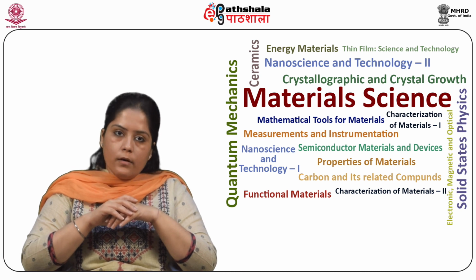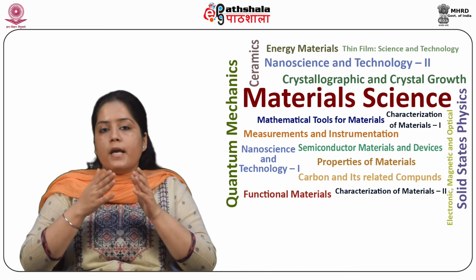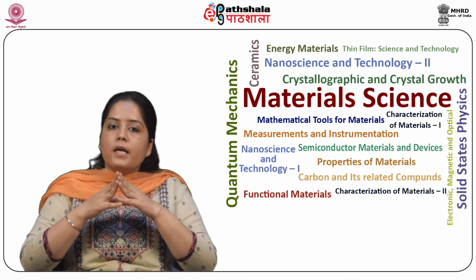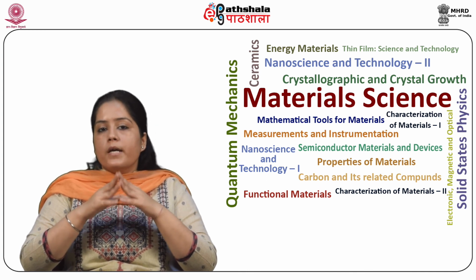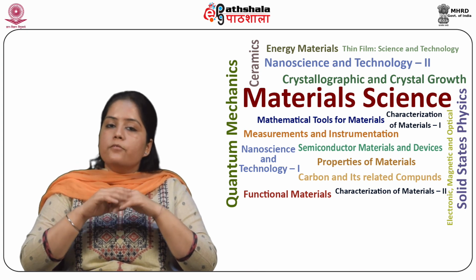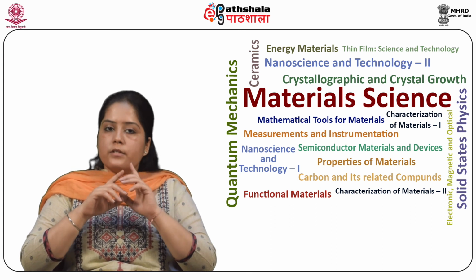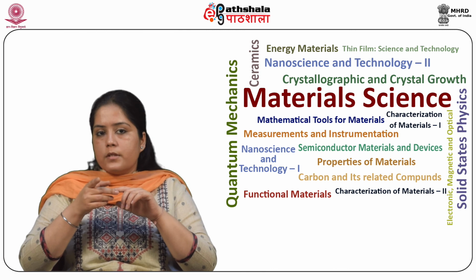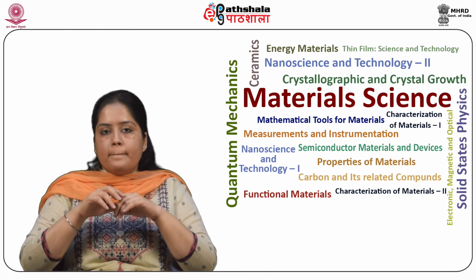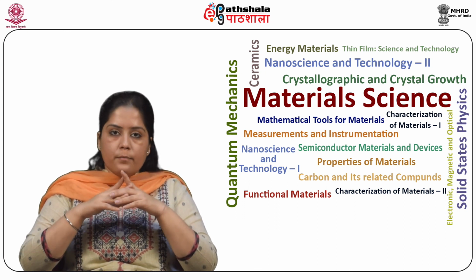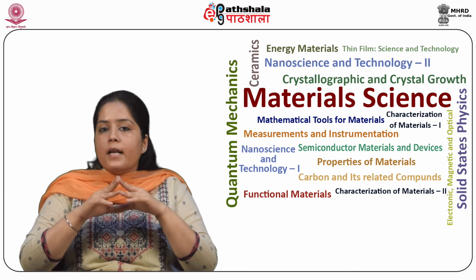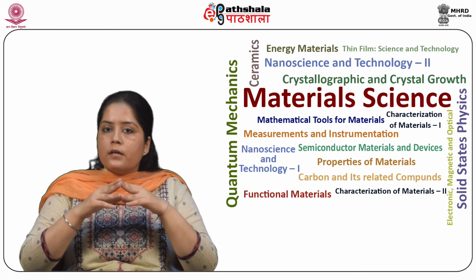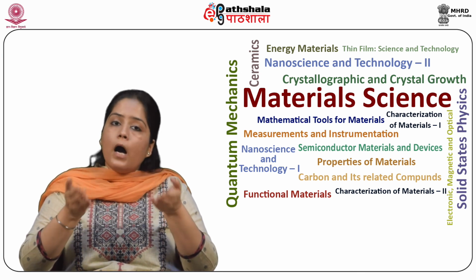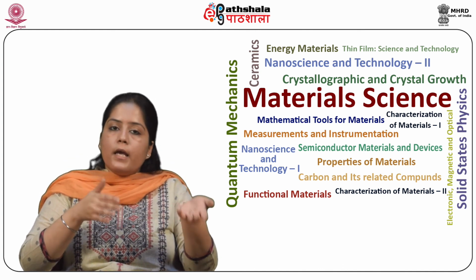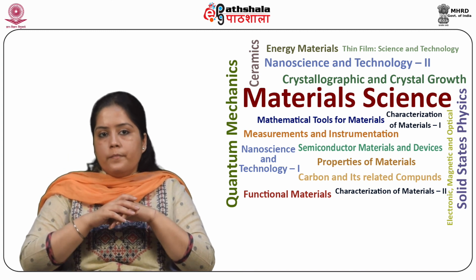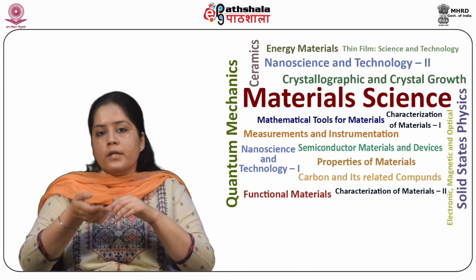Normal spinels, examples are ZnFe2O4, MgAl2O4, CoAl2O4. Now, in the chemical formula, A is represented by the tetrahedral site and B is represented by the octahedral site. The inverse spinels, for example Fe3O4, NiFe2O4, have half of B on the tetrahedral site, along with A, and the remaining B on the octahedral site, with 8 formula units per unit cell.